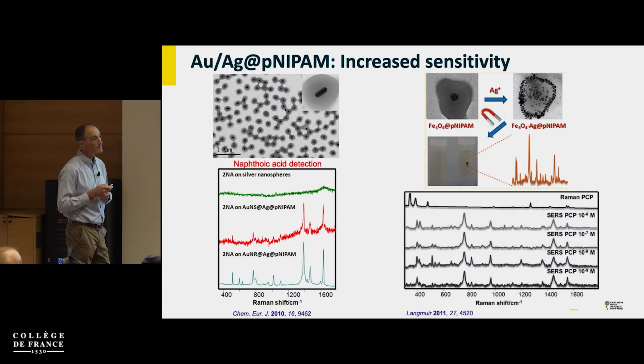Why don't we have the signal of the polymeric shell in the Raman or SERS? That's a good point. So styrene actually provides a rather good Raman signal. We have never been able to see a strong signal in polystyrene. So it might be that the polymeric shell that is covering the cores before the polymerization is sort of screening the contact with the metal particle, and we don't see much effect of the polymer there. But it's a very good point, and we never understood it very well. But this is what we find in practice, that the polymer is not providing a sufficiently strong signal.